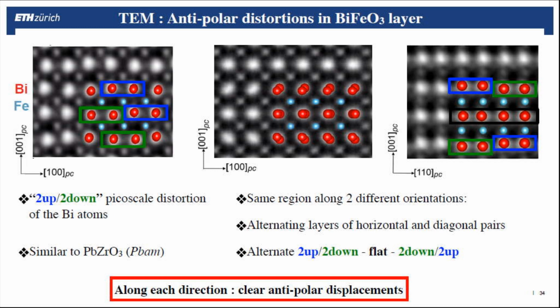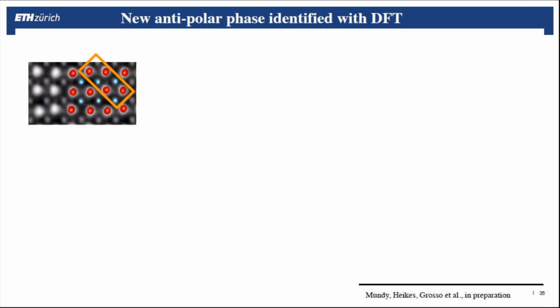And what they see here is that you can notice that you have a displacement in plane, diagonal, and the opposite diagonal, and it alternates. And when you rotate this, you see 2 up, 2 down, flat, 2 down, 2 up, and it continues the repetition. So from these images, it is clear that there is an antipolar displacement in each of the directions that we are considering here. So now let's go to the theory side and see how we can identify this structure. To do that, we can consider different arrangements of atoms and solve them numerically, so compute the energy and see which are stable, which are unstable, and which are low energy.